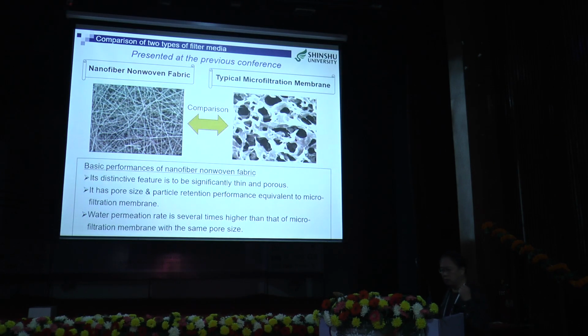At the previous conference, we discussed the comparison of the filtration performance between nanofiber non-woven fabric and typical microfiltration membrane. To summarize the basic performance, the distinctive feature of nanofiber non-woven fabric is to be significantly thin and porous. The nanofiber non-woven fabric has pore size and particle retention performance equivalent to microfiltration membrane. Water permeation rate is several times higher than that of microfiltration membrane with the same pore size.